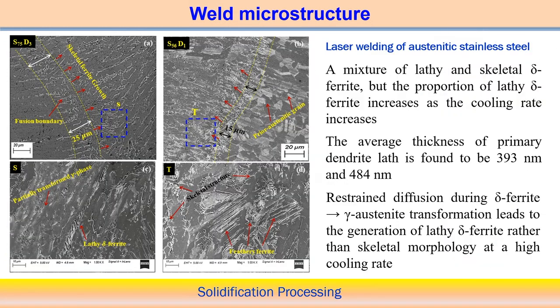Here is another example associated with weld microstructure, which occurs in the laser welding of austenitic stainless steel. If you follow the figure, here you can see the microstructure. If you observe it, we see all different kinds of structure. Here you see the fusion boundary. The fusion boundary zone, from the microstructure you can identify, is around 25 micrometers. And here you can see the lathy delta ferrite structure, feathery ferrite structure, because the morphology we can see from the diagram also. Here a skeletal structure can also be formed.